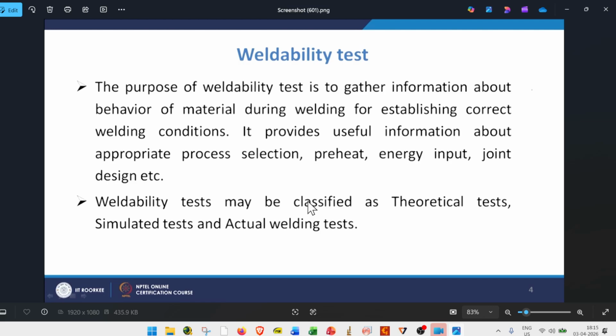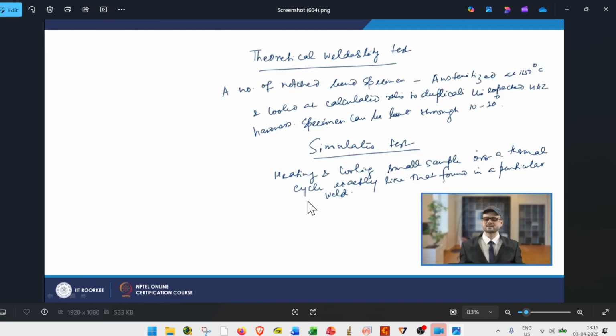Next, weldability tests may be classified as theoretical tests, simulated tests, and actual welding tests. The theoretical welding test is this: in the case of steels, we will do annealing up to 1150 degrees. Then we will cool it to replicate what kind of situation occurs during the welding condition. Once the annealing is done, we will do the bending of that weld bead to 10 to 20 degrees.